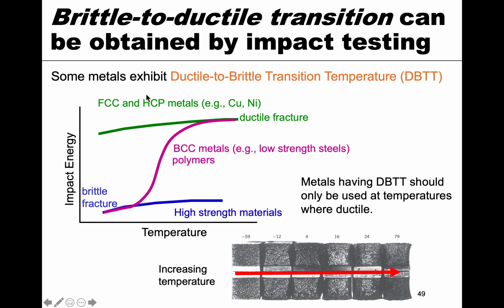So these are things like FCC and HCP metals, so copper, nickel. And then we have high strength materials that are rather brittle. And you can see that they also can exhibit changes, but they're pretty subtle. And so they always kind of have low impact energy. However, you can have things like BCC metals, the lower strength steels, and also polymers that are ductile as well, where at high temperatures they follow the ductile behavior, and then there's this transition, kind of an S-shaped curve here. Then there's a transition at a specific temperature to the brittle, and so as temperature decreases, the energy they can withstand before fracture decreases, and so they become more brittle. So this is obviously important if temperature is going to be an issue with the application. So that's something that we have to consider.